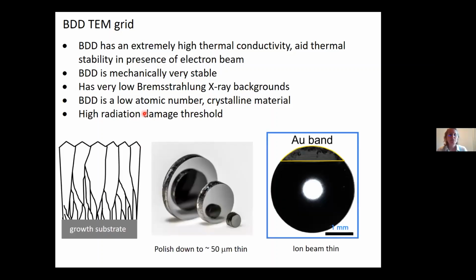So how do we make them? We grow by chemical vapor deposition. We have a growth substrate and we grow thick actually. For electron beam transparency, you're really looking at trying to keep your thickness probably below about 100 nanometers. And we might grow thick to 300 microns. So what we do is we pop it off the growth substrate. So the whole thing is freestanding boron doped diamond, and it's polished to a very fine surface finish here, and also would be polished to a very fine surface finish here, and we thin it down effectively.